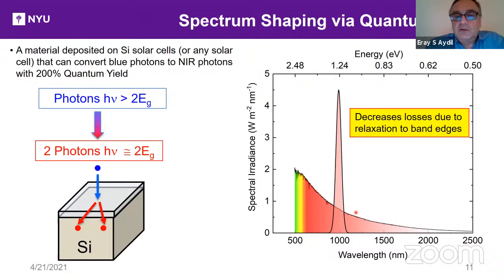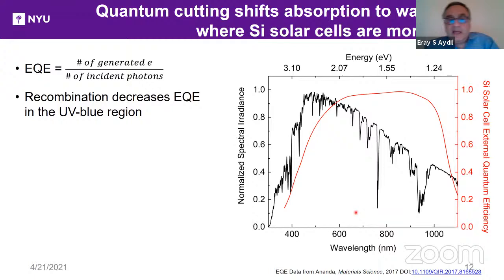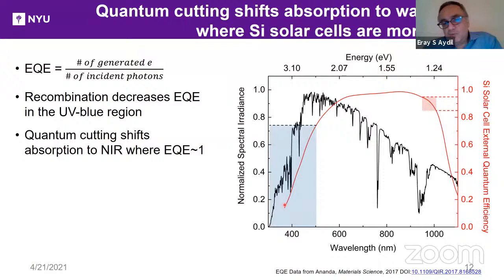Now, there's another benefit, and that is quantum cutting shifts absorption to wavelengths where the silicon solar cells are more efficient. So one way that we look at the efficiency is using the figure of merit called the external quantum efficiency. That is the number of generated charges per number of incident photons. So here I plotted the spectrum. This is the solar spectrum, AM1.5, it's normalized. And I also plotted a typical external quantum efficiency for a silicon solar cell. Now the recombination decreases the external quantum efficiency in the UV blue region. So you can see here that the EQE is taking a dive once we get into the blue region. Quantum cutting shifts absorption to near infrared where the external quantum efficiency is closer to one.